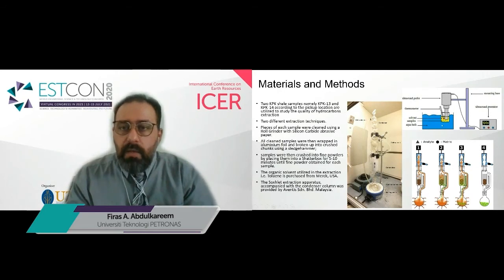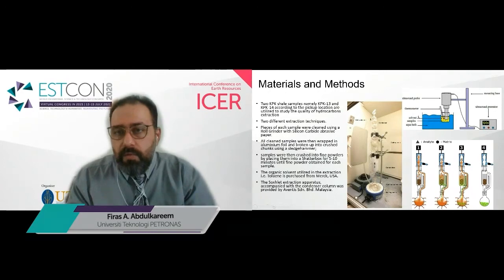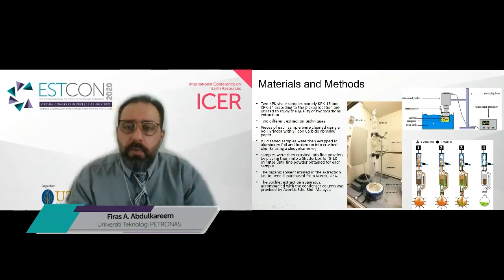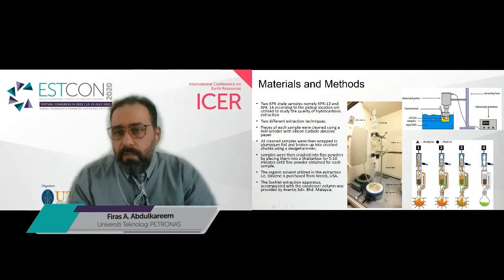On the other side, for the ultrasonic assisted extraction technique, the sample used is usually 50% of the amount utilized in the traditional extraction technique. In this case, toluene is used at around 10 mL in the ultrasonic assisted, while around 20 to 40 mL is used in the traditional technique, which is the hot reflux. Since the ultrasonic probe generates a lot of heat, the solvent and the samples need to be cooled down during the process. That usually takes around 15 to 30 minutes compared to the 24 to 48 hours of